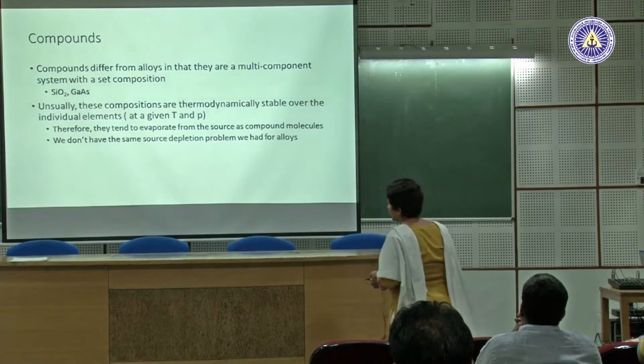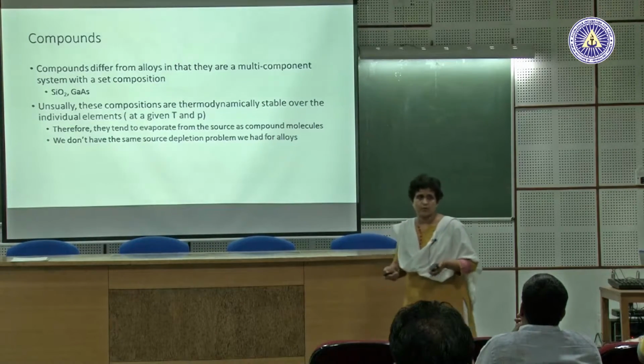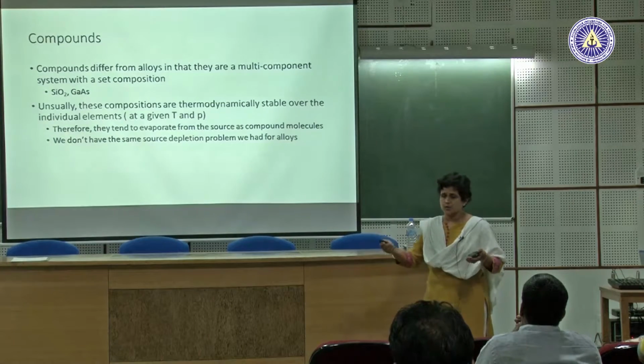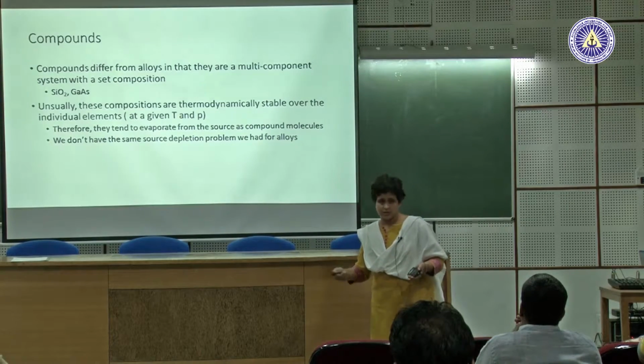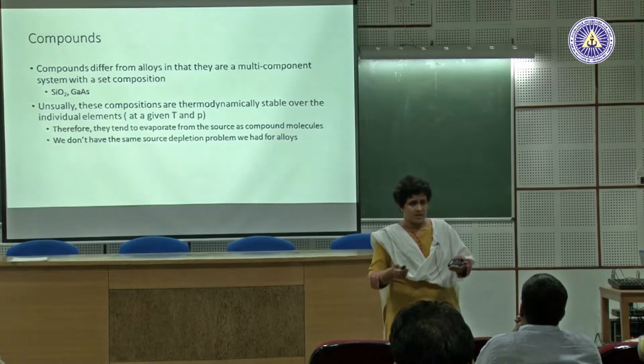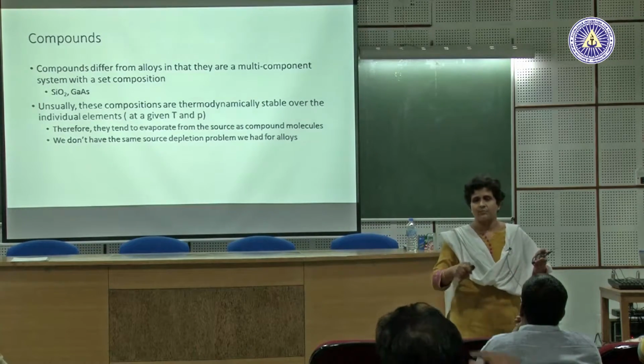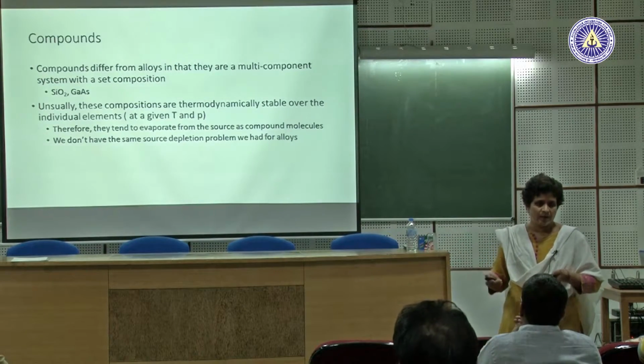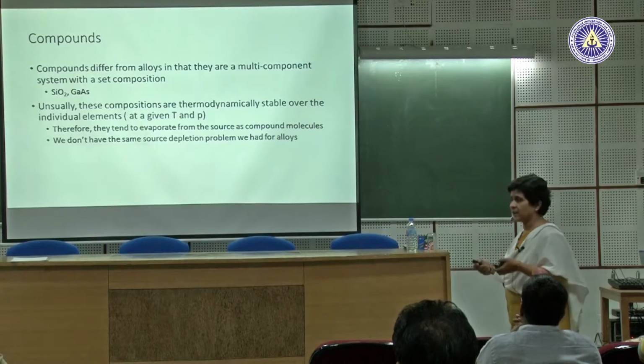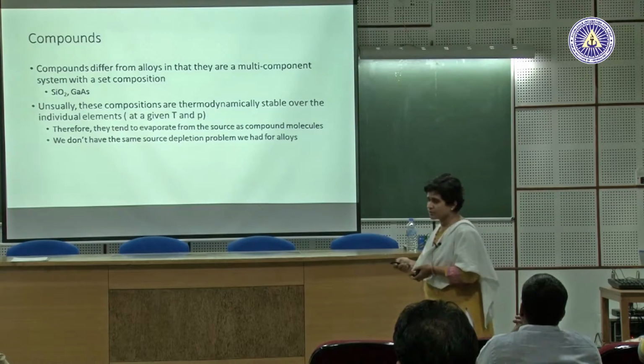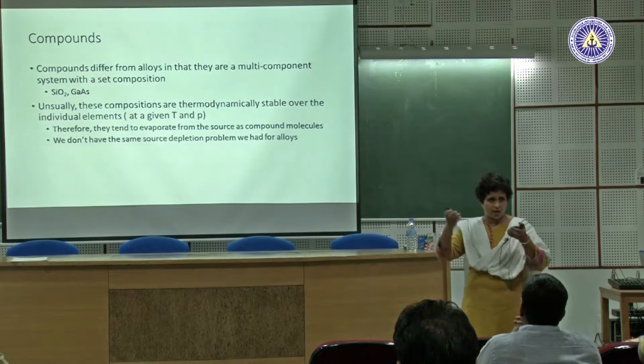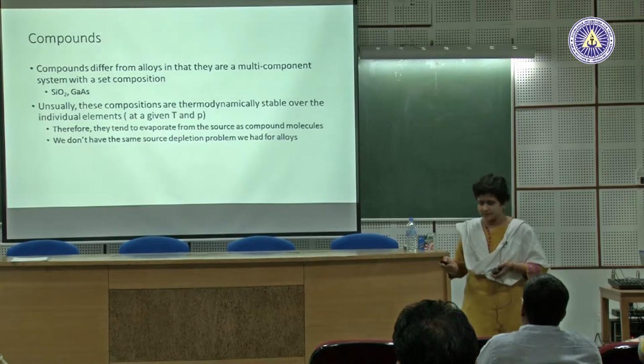Compounds are another issue, on how to get the right stoichiometry. If I want to deposit silicon oxide, how should I control the evaporation rate of silicon and the oxygen present in the chamber such that I always get SiO2. I don't get something like SixO, right. So, there is again a lot of material science and physics that goes into understanding how the evaporation rates and the surface reactions are taking place.